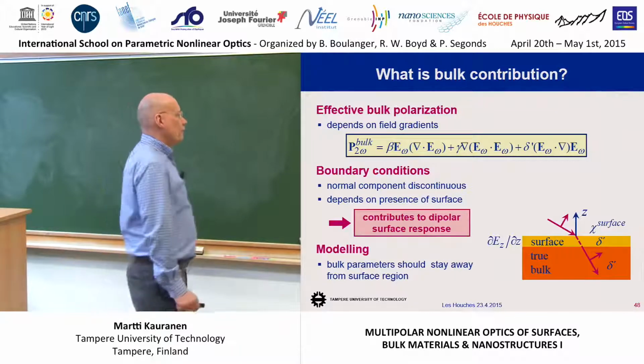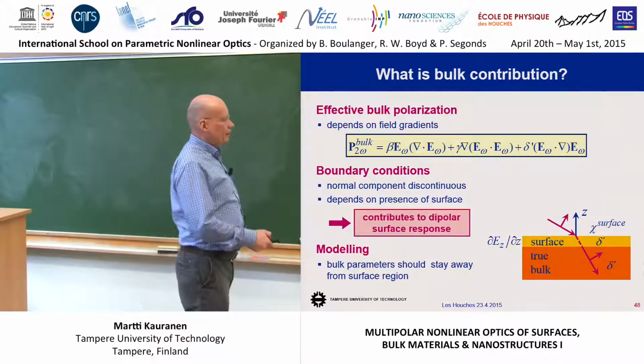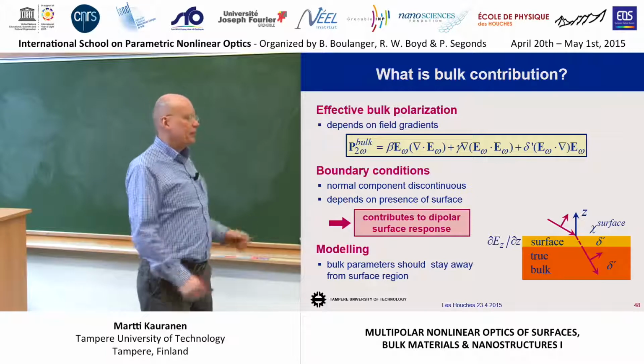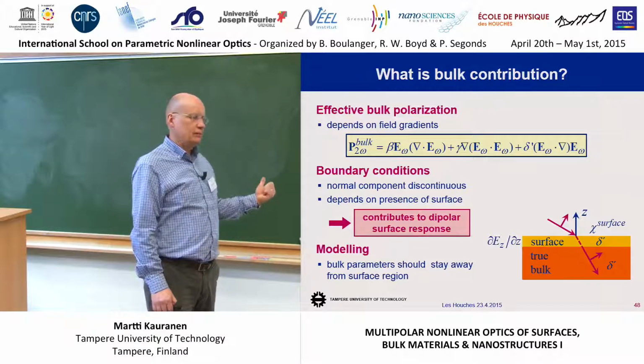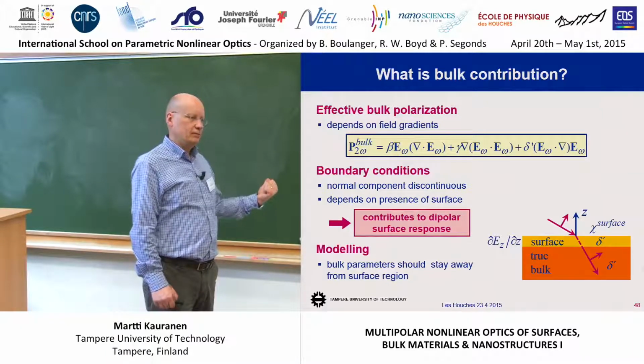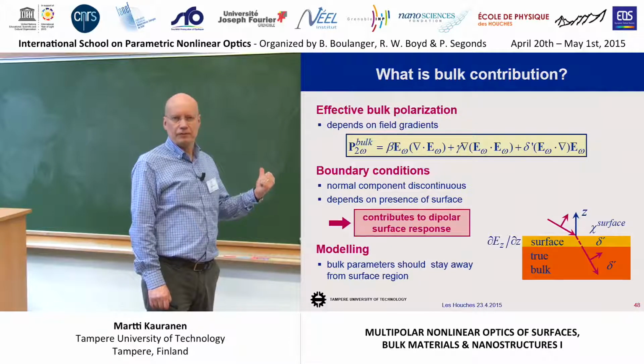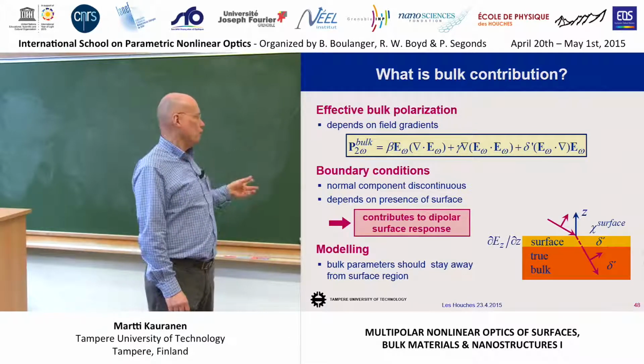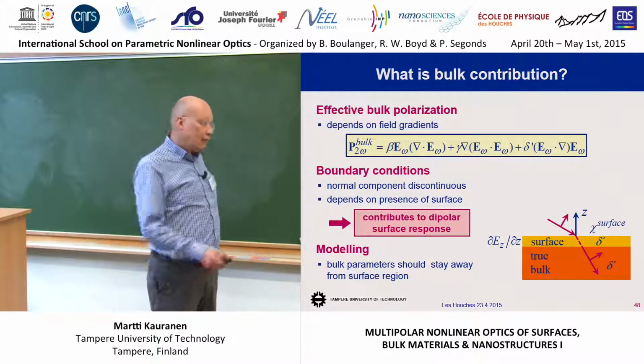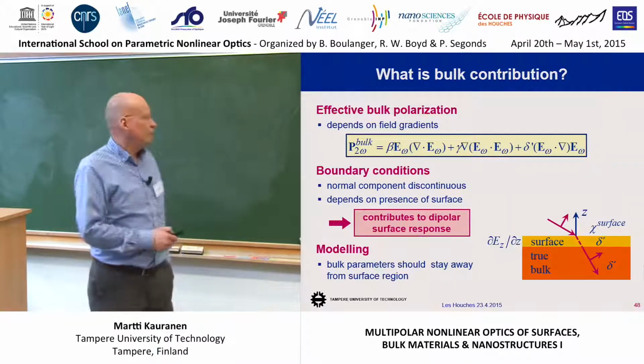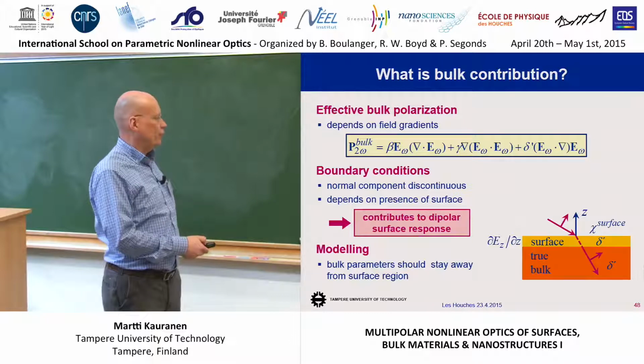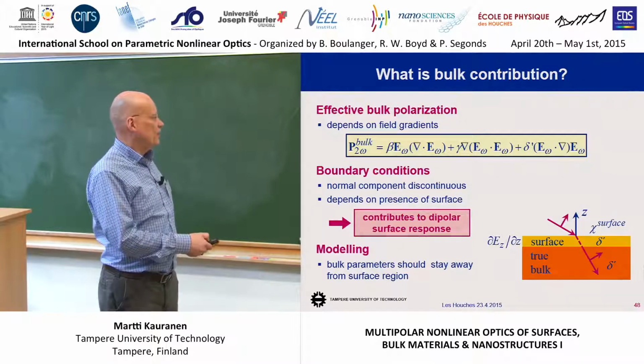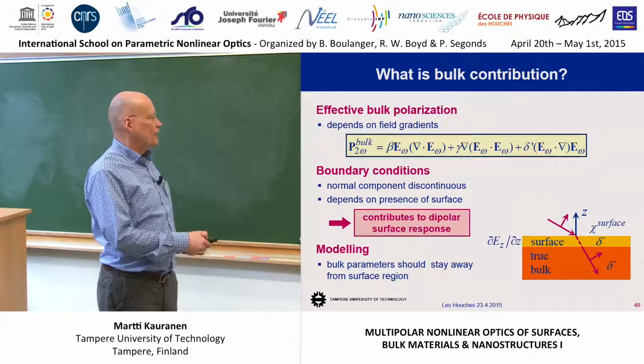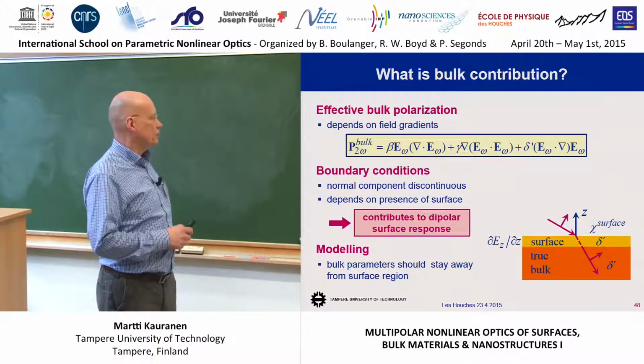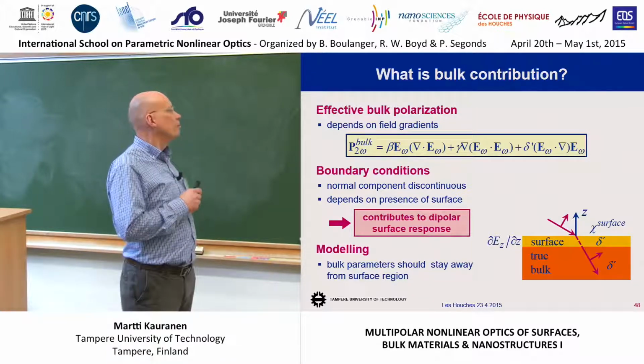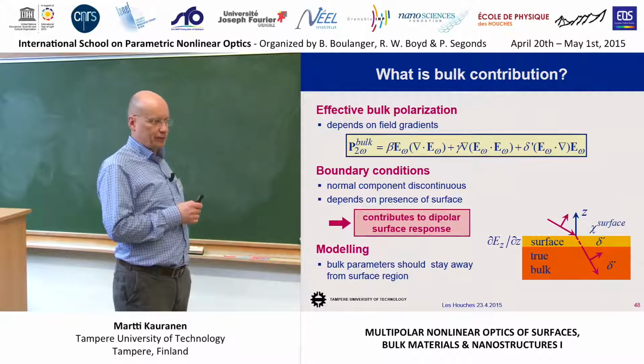The question is whether this response, which is described by a bulk parameter and field gradient, is the bulk response or the surface response. In my opinion, it's a surface response. There are some old papers by Shen where he showed that when you do this in a number of different ways, this response contributes to the effective dipolar surface response. And that's fine.